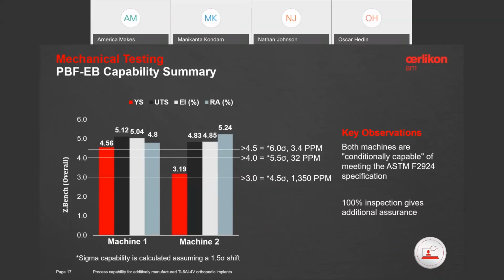Here we've dashboarded the Z-scores for all tensile data for both machines to see how they match up against each other. A small machine-to-machine variation can be seen, with machine number 1 performing significantly better than machine number 2 on yield strength. With that being said, both machines are highly capable of meeting the ASTM F2924 specifications at a sigma level of at least 4.5. To further monitor the process, we also perform 100% mechanical inspection of every production build, and this gives us additional assurance that the parts will be within spec.